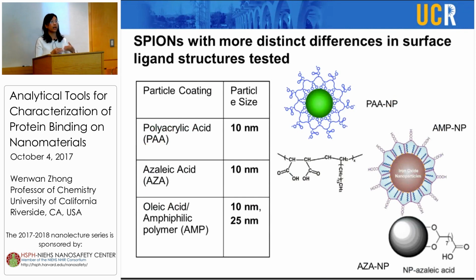So polyacrylic acid is hydrophilic, azelaic acid is the most hydrophobic within this group, and the amphiphilic one has the in-between hydrophobicity. So we want to see, although all of them carry carboxyl groups on the surface, they have some hydrophobicity differences, and whether they would form different kinds of corona on the surface. And for the amphiphilic polymer coated particle, we also compare the one with a smaller core size and the one with a larger core size.